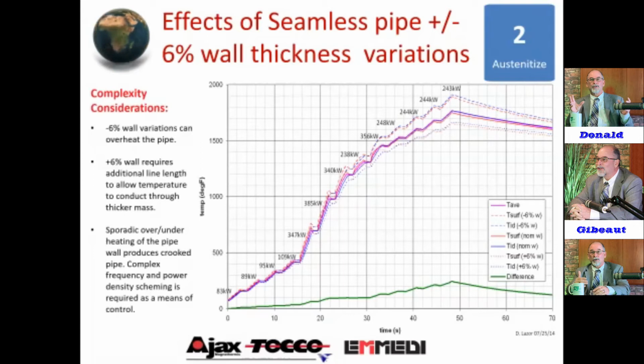So we did a joint development project over a couple of years on one of our lines with US Steel here in the US, on seamless. They were running seamless through an ERW design line. And we discovered everybody was more concerned about the thicker wall in the variation, not heating it through, but that we could compensate for with power and the frequency selection. It became the thinner side of that spec that overheated and caused the pipe to hook.